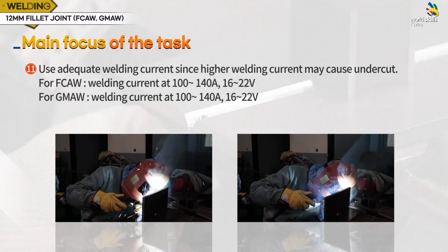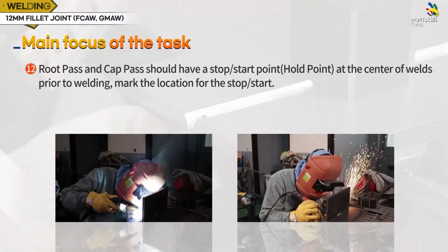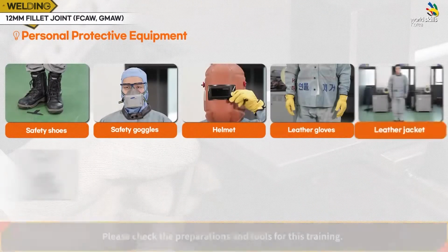For FCAW, welding current is at 100 to 140 ampere, 16 to 22 volt. For GMAW, welding current is at 100 to 140 ampere, 16 to 22 volt. Root pass and cap pass should have a stop-start point, hold point, at the center of welds. Prior to welding, mark the location for the stop-start. Please check the preparations and tools for this training.